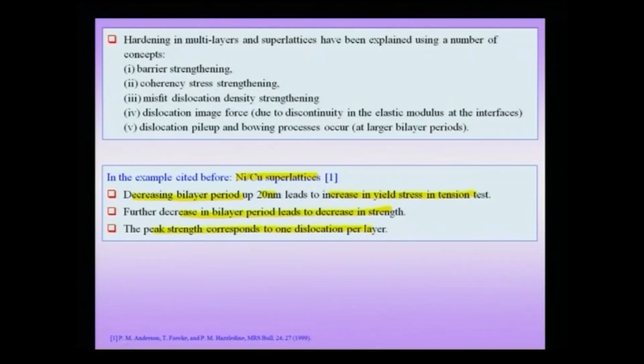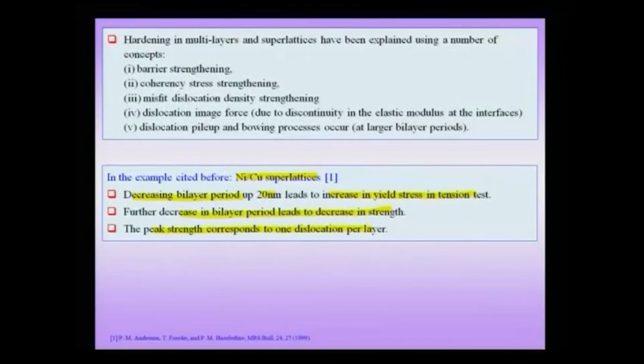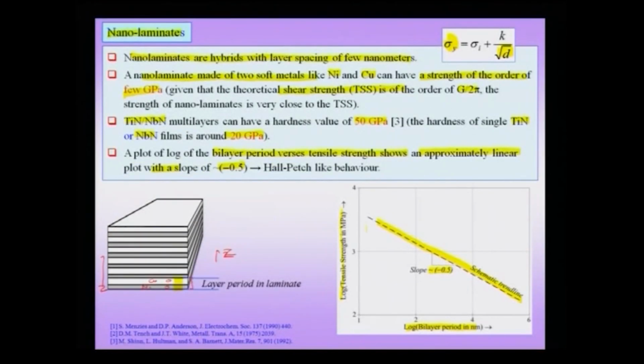So this linear trend is of course followed in a certain regime, as I pointed out, and would not be followed in a very large period. But the interesting thing is that the peak strength corresponds to about 1 dislocation per layer, and of course we will soon see what is the mechanism which has been attributed to this kind of a strengthening.